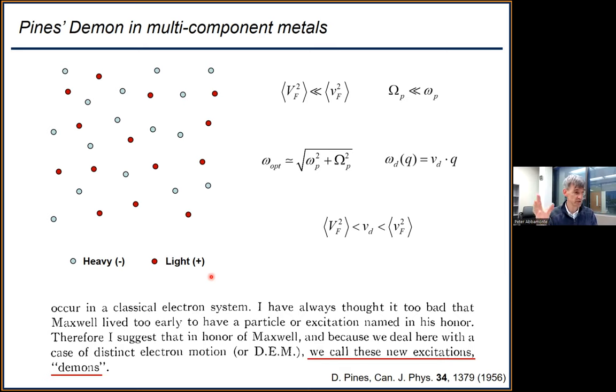At any rate, let's suppose you have this system and then you ask, what is the plasmon of this system? So this is what he considered in this early paper. The way he framed the problem is he said, okay, if I took away the red particles and I only had the blue ones, that would have a plasmon. If I took away the blue ones and I only had the red ones, that would have another plasmon. So if I have both, I should have two plasmons, one from each bath, though the two may interact with one another. And then he went through some mathematics and arguing.